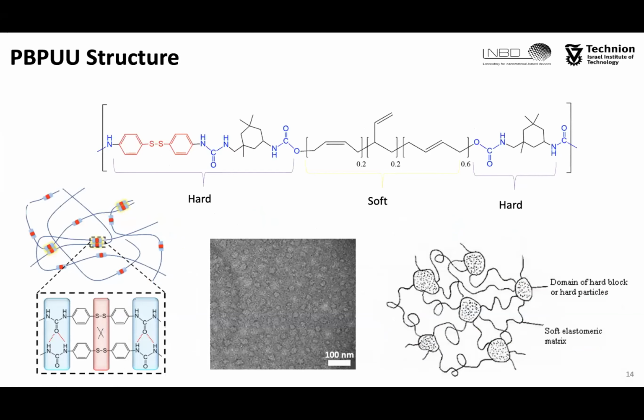In order to understand what is going on with these polymers, we ran molecular dynamics simulations, and we showed throughout these simulations a separation between the soft and hard regions of the self-healing polymer, something we confirmed by TEM analysis.